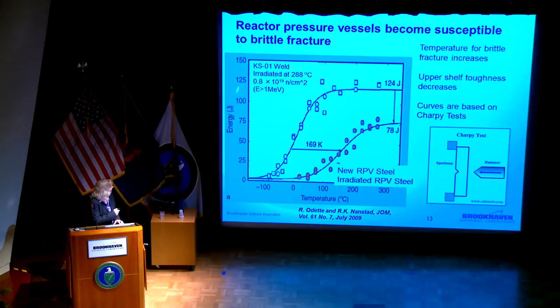This chart shows the fracture energy for pressure vessel steels versus temperature. The blue graph is new reactor pressure vessel steel. You can see down here, this is brittle failure, but it's happening at minus 100 degrees Celsius. This is not really a temperature regime you would ever see with a reactor pressure vessel, so you don't have to worry about brittle failure in new material. Then it transitions, the material becomes harder and harder to break until you get to completely ductile failure. After you irradiate the material, you shift the temperature where this change to brittle failure occurs to a much higher temperature. Now you have to worry about brittle failure at temperatures over 100 degrees C, 150 degrees C. This starts to impact your operations and how you're able to run the plant and the reactor.